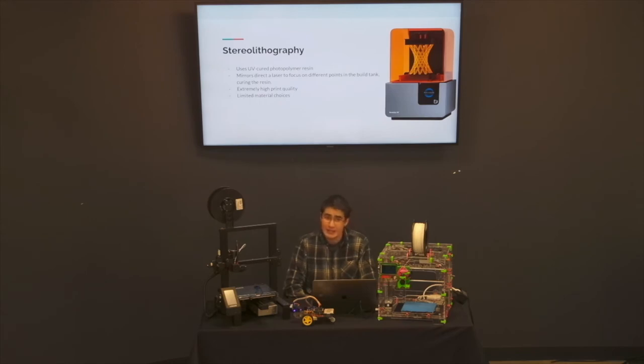You can achieve much higher print quality than most other print systems or manufacturing methods with an SLA printer. The biggest disadvantage is that you don't have a lot of materials to choose from. You're basically stuck to photopolymer resin, and resins like that aren't particularly strong. They also tend to cure when exposed to UV light after they've been finished. So if you were to take an SLA printed part and leave it outside, the UV light would degrade it extremely rapidly. So there's that to consider.